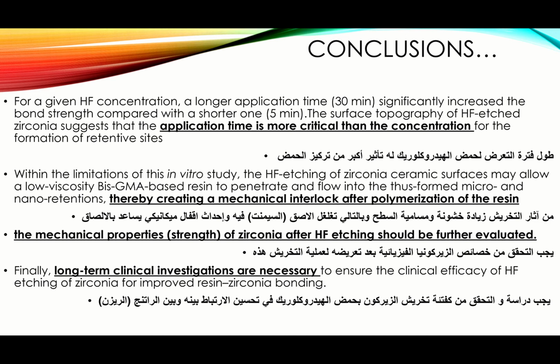Now, the mechanical properties or strength of zirconia after hydrofluoric etching should be further evaluated. Absolutely. This is a new way of doing things, so to speak, and we want to see what kind of mechanical properties, especially since you're talking about surface roughening again. And surface roughening in zirconia, in the back of our minds, has an issue, because you're talking about even LTD, low temperature degradation. The problem of low temperature degradation is surface roughness and then micro cracks.